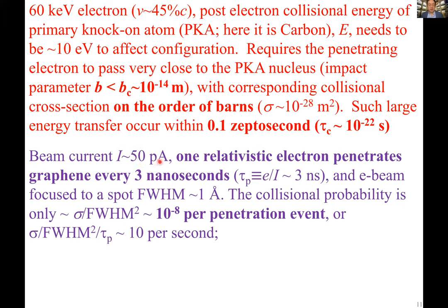So we have a beam current of 50 picoampere. So we actually have one electron penetrating this graphene layer every 3 nanoseconds. So in 1 second, hundreds of millions of electrons penetrate. But only one out of 100 million can get within this one barn of an area. So even when we focus the electron beam to an angstrom squared, one barn out of an angstrom squared is still one out of 100 million. And so we get about 10 direct hits every second. So that hand that you see has that kind of hit rate.